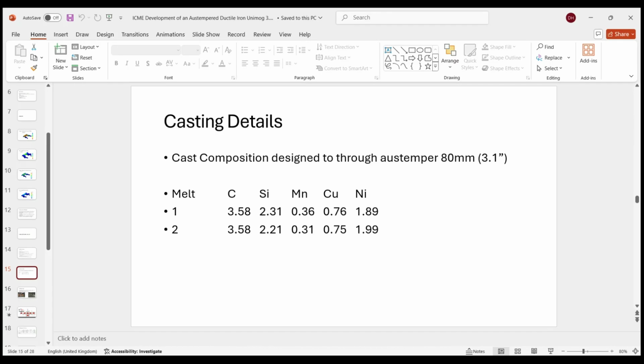We can through-austemper sections up to 200 millimeters, even higher. We have proven we can do 250 millimeters. But this casting is around 80 millimeters. So when we discussed and looked at the alloy, we went with something around 0.75 copper and 1.8 to 1.9 nickel.